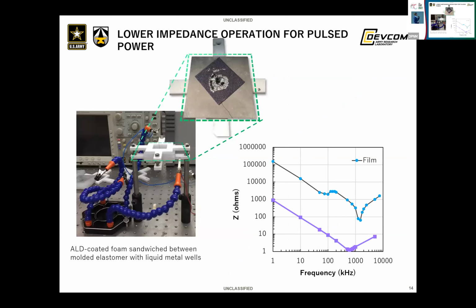Now, if we wanted to infiltrate and test the foam, I had to develop a soft microfluidic liquid metal input strategy to try to get the liquid metal in there. I don't know why Nazanin thinks this is so funny. It was really arduous to get this to work, but there are internal channels and wells that I micromolded, and then this is what an actual infiltrated foam looks like. This is why I used that computer generated picture. And this is the test setup. So here's the pre-threaded ground wire, which is clamped and accessed over here. And then there's a wire that is sitting in a well of liquid metal, which has continuity with the rest of the liquid metal inside of the foam.